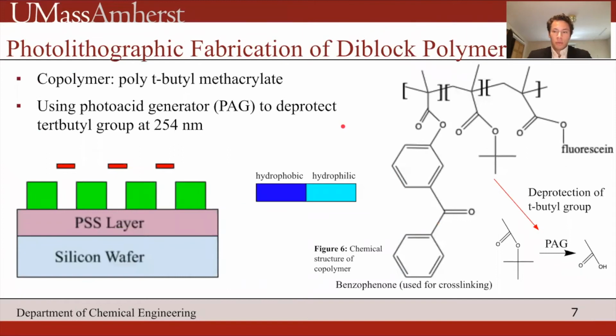The next step is to transform these ribbons, or parts of these ribbons, from hydrophobic to hydrophilic. Again, because the hydrophobic component would be wrapping around the oil droplets, and the hydrophilic component would be extending in the solution. And so the polymer that we're using is the same polymer discussed in the previous paper, poly tert-butyl methacrylate with trace benzophenone shown on the left and fluorescein, where benzophenone is used for cross-linking and cross-links at 365 nanometers, and fluorescein is used for optical microscopy. This tert-butyl group can be deprotected using 254 nanometer wavelengths when a photoacid generator, or PAG, is mixed in with the polymer, which causes this tert-butyl group to deprotect, shifting the methacrylate group to a carboxylic acid, and thereby shifting this polymer from hydrophobic to hydrophilic.